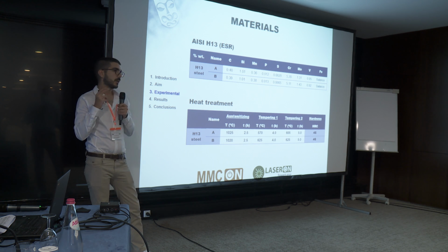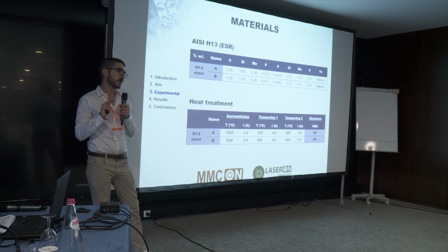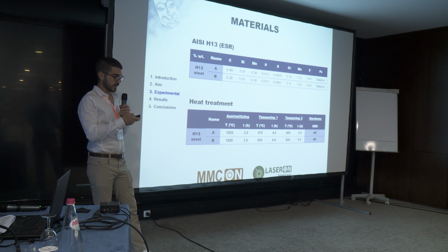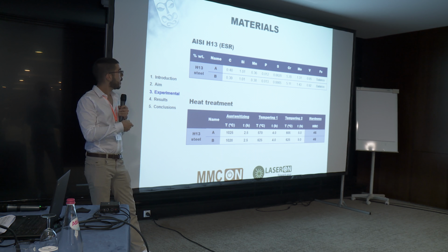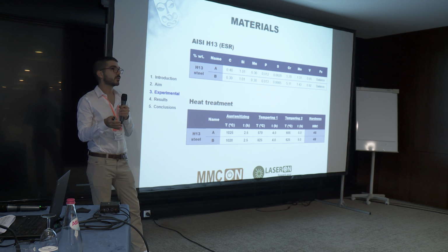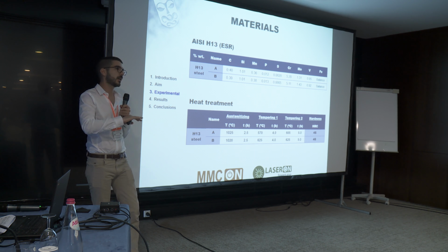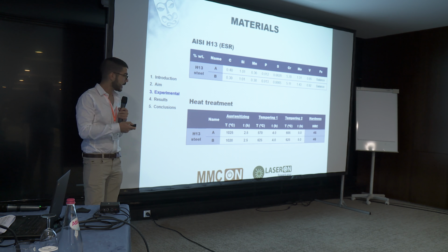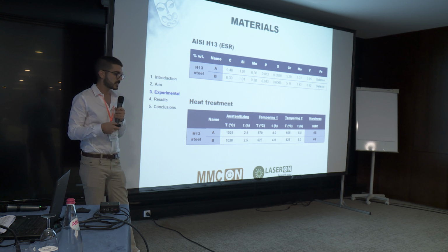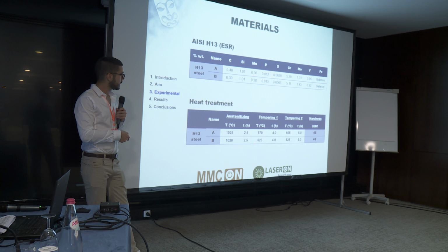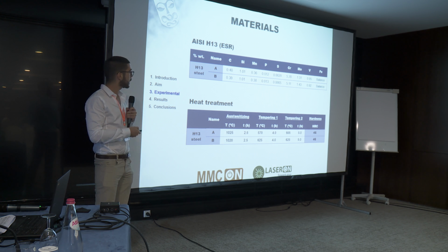First of all, we tested two materials under the same H13 specification. As you can see, the weight compositions are pretty much the same, but they belong to two different manufacturers. I will refer to them as A and B. And the heat treatments they were subjected to were meant to reach the same final hardness of 46 in the Rockwell C scale, but as you can see, the tempering temperatures of B steel were a bit higher. We will see how this may affect it.